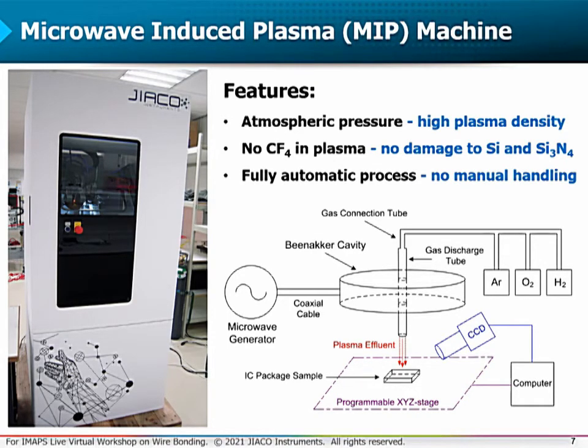The MIP machine operates at atmospheric pressure, and this means that the mean free path of ions is extremely low, so that only long-lived oxygen radicals in the plasma effluent will actually contribute to etching. In the MIP system, the plasma beam is confined, and sample heating is directly through the plasma effluent.